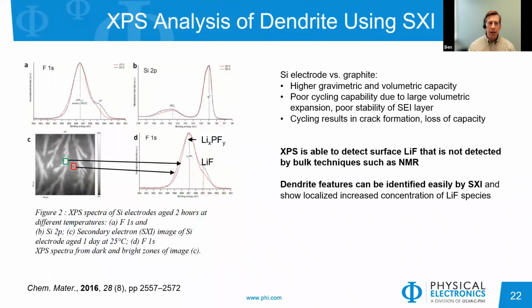Another area of concern is dendrite formation. These can evolve from defects on our electrode material, and then, as you see here, sprawl out and eventually maybe cause short circuiting or other deleterious effects.